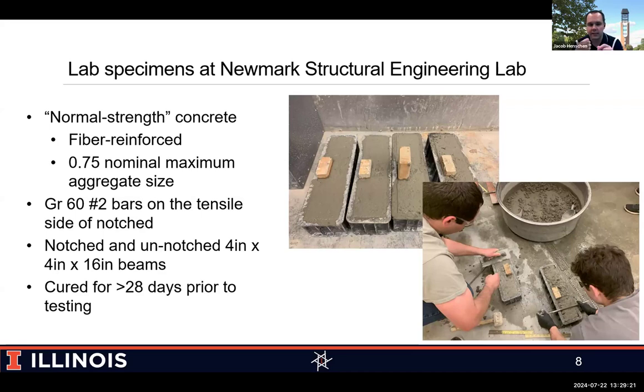Now, with that in mind, I did come back and add some fiber reinforcement, because as we start to create these internal stresses, I didn't want there to be just a crack and all of a sudden we lose the specimen immediately. I just wanted it to be a little bit easier to work with. So there was roughly 1 pound per cubic yard of polypropylene fibers added to the mixture. Very, very low dosage, only meant to hold things together. Some of the specimens we did add some reinforcement to, really small bars, once again more for crack control than anything else.